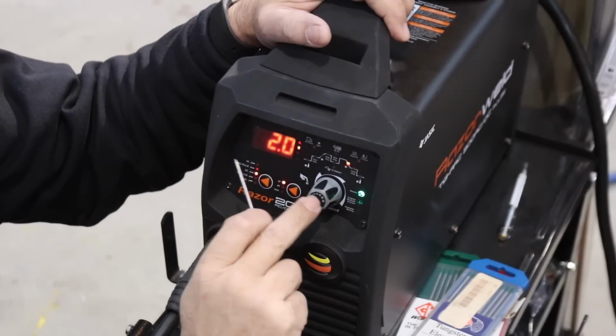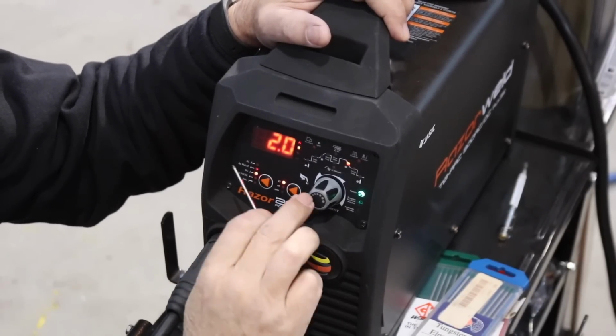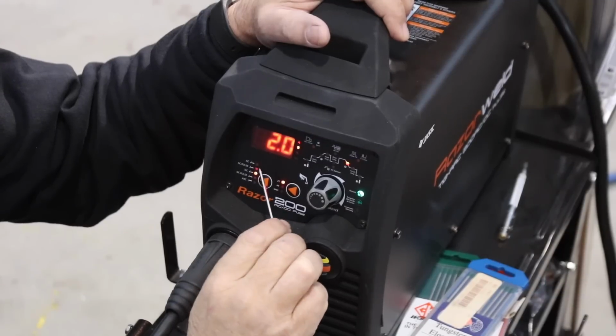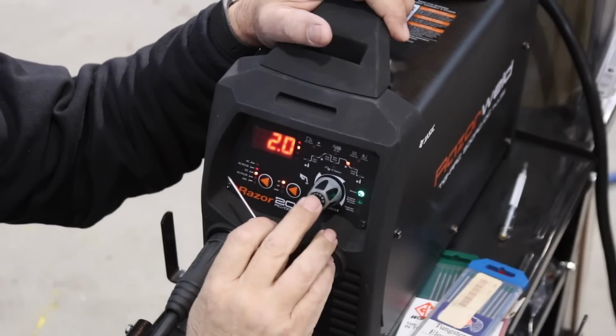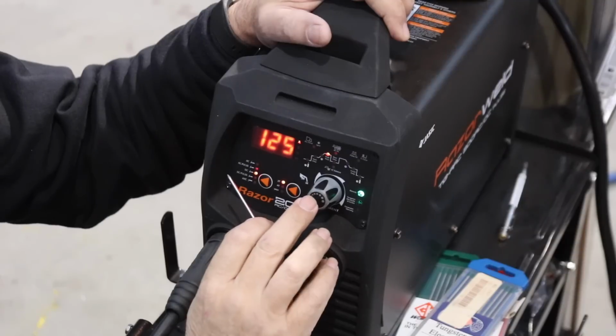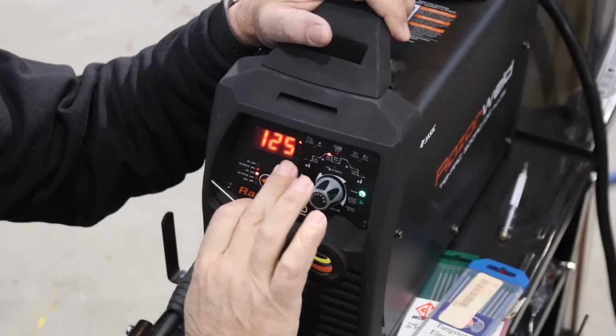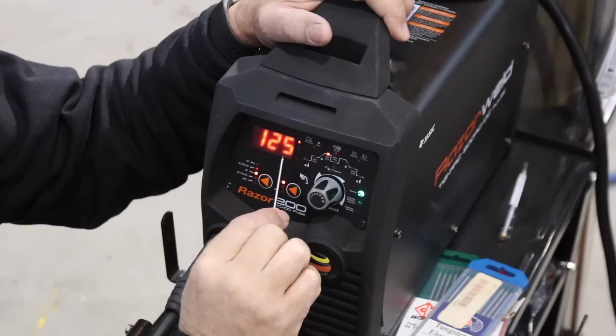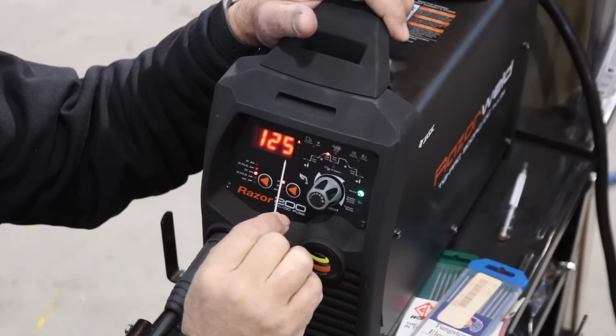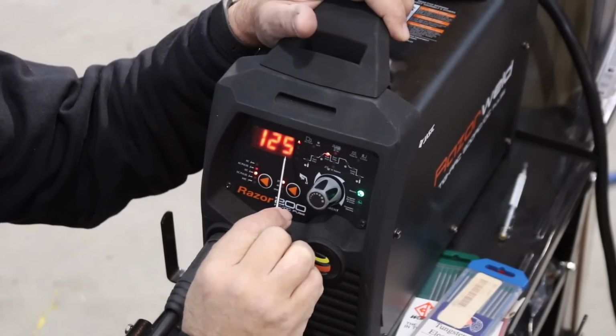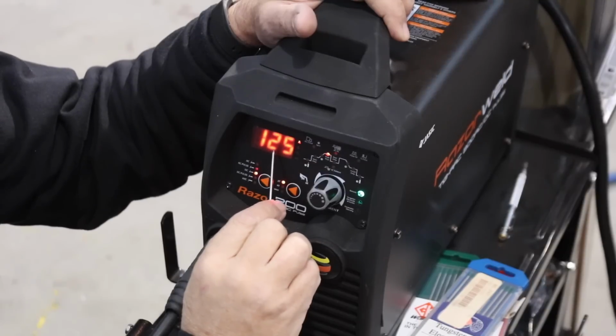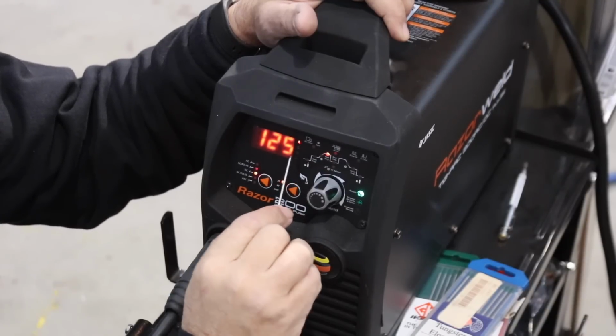Downslope, 2 seconds. You can set that however you need it. And what's the downslope again? That's tapering off the amperage when you're finished welding and you want to taper down to your end amperage. Let's say you're using the torch switch, welding at 125 amps, going along fine, but now you get to the end of the metal.